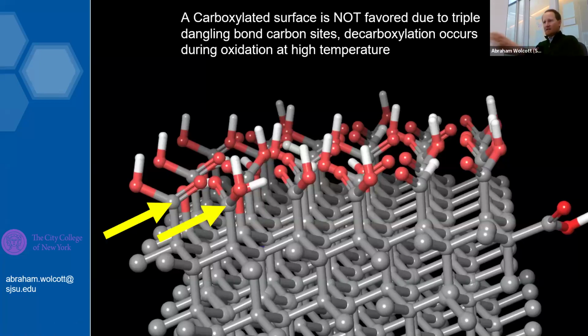So it leads us to this picture, and I think this is an important aspect of this work. A carboxylated surface is not favored due to triple dangling bond carbon sites. In order to have a carboxylic acid, this carbon needs to only be bound by one carbon-carbon bond. And decarboxylation occurs during oxidation at high temperature. This bond is broken and the CO2 will leave the surface.